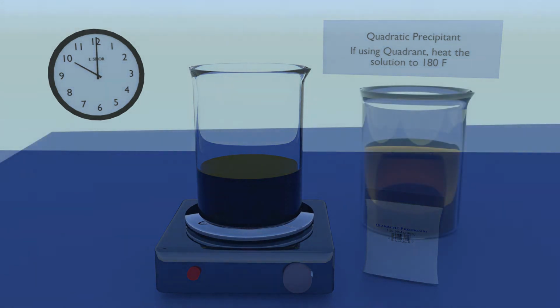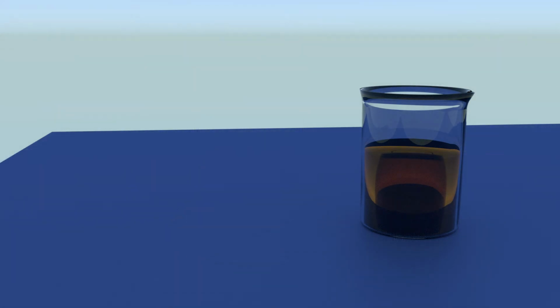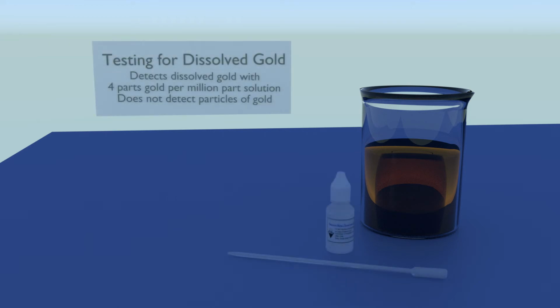Testing for dissolved gold. Before pouring off the waste solution, you will want to make absolutely sure that 100% of your dissolved gold has precipitated out of solution. For this test, you need precious metal detection liquid. You can buy this ready-made, or you can put it together yourself. Basically, it's concentrated HCl, infused and saturated with stannous chloride and very pure tin.